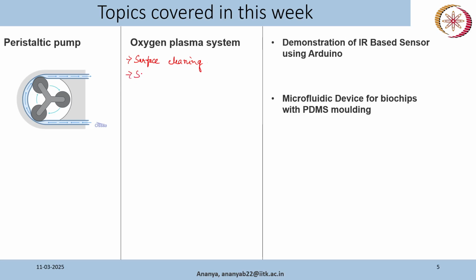Next, it is also used for surface activation and bonding. Okay, the example is PDMS with glass that was shown in the class. So basically what the oxygen plasma does, there will be some ions in the plasma that will create some dangling bonds on top of our substrate surfaces, and when we press them against each other, there will be formation of some kind of covalent bond, and that basically binds the two substrates. Okay, so you can see what kind of bonding happens between PDMS and glass due to the oxygen plasma system.